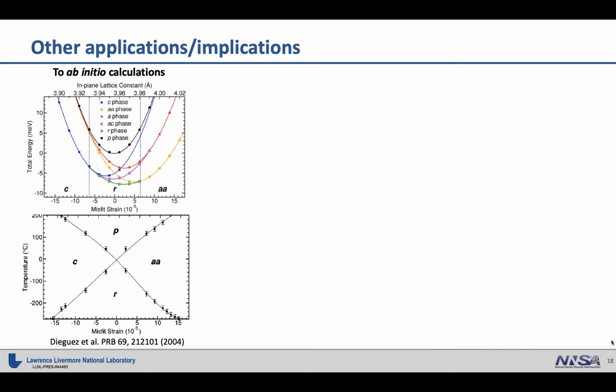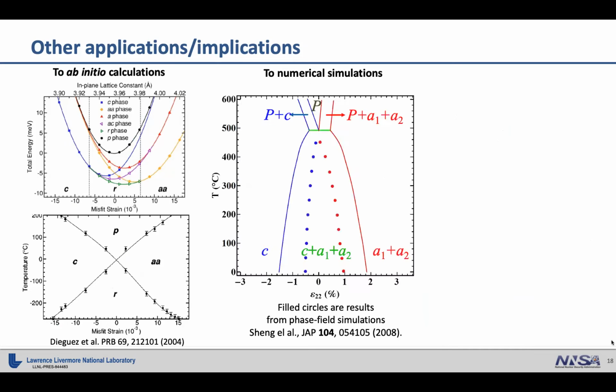For example, for ab initio calculations, when you obtain the total free energy as a function of the misfit strain, you may want to go a step further and construct the common tangent, which may give you the two-phase regions purely based on ab initio calculations. And for numerical simulations, such as phase field simulations, our method, although it's not very accurate in predicting the domain boundary, gives you a hint, like an upper bound or lower bound, on how to select and speed up your simulation by performing fewer simulations around these phase boundaries predicted by our approach.